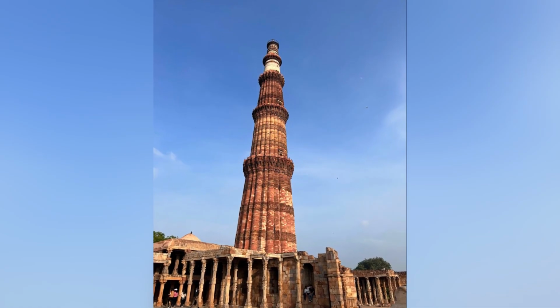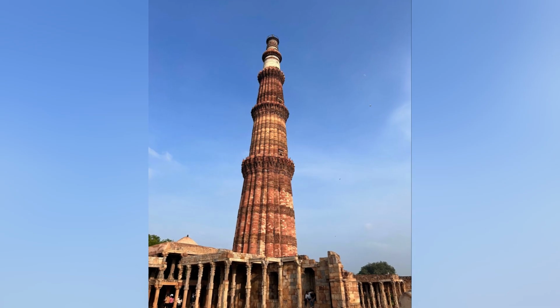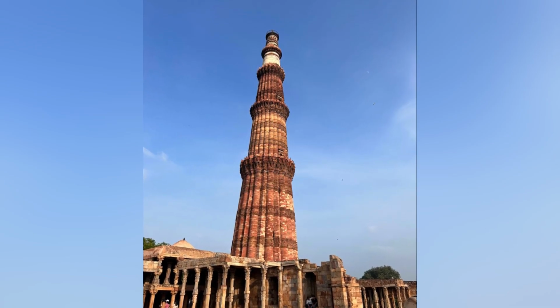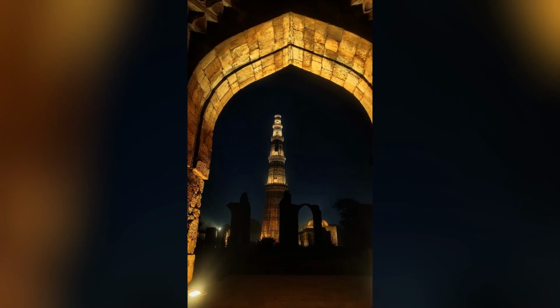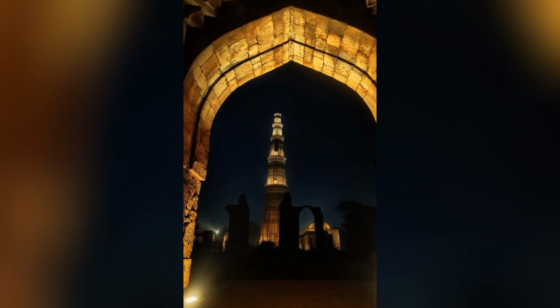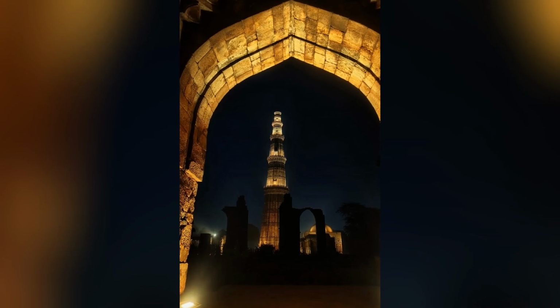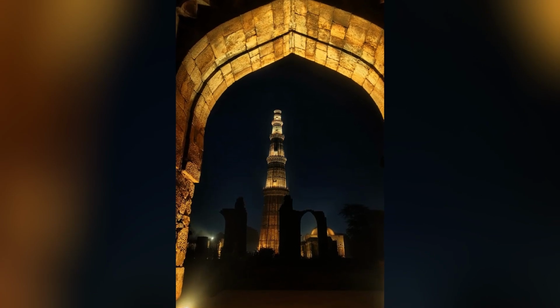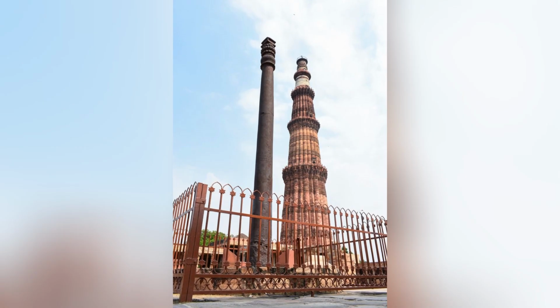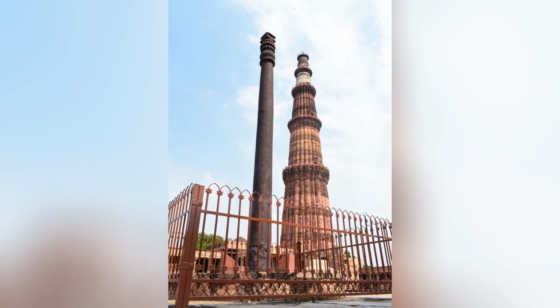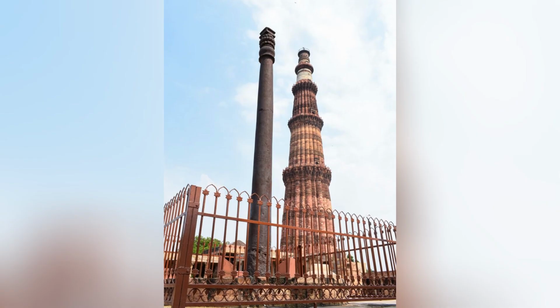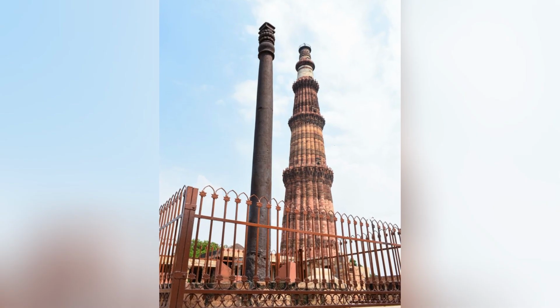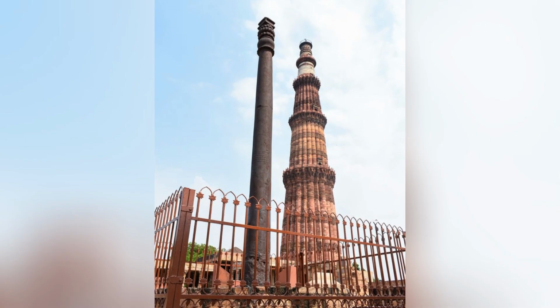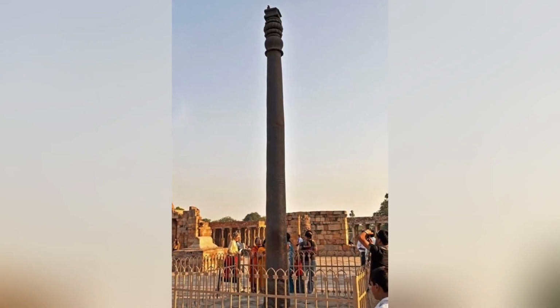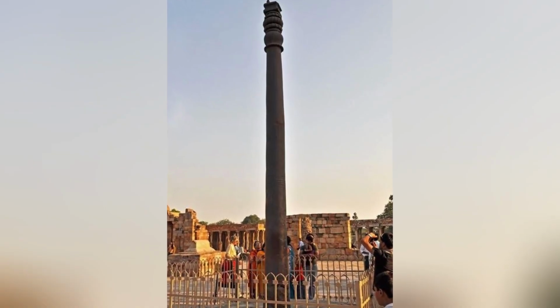The iron pillar of Delhi has lost virtually none of its surface over 1600 years. The inscription on the pillar, which was engraved at the time of the pillar's erection, is still clearly legible, with the letters sharp and well defined, showing none of the erosion or the pitting that would be expected if the pillar had been subjected to significant corrosion. The surface of the pillar is smooth and uniform, covered by the thin, dark grey protective film that Balasubramaniam identified as iron hydrogen phosphate hydrate.